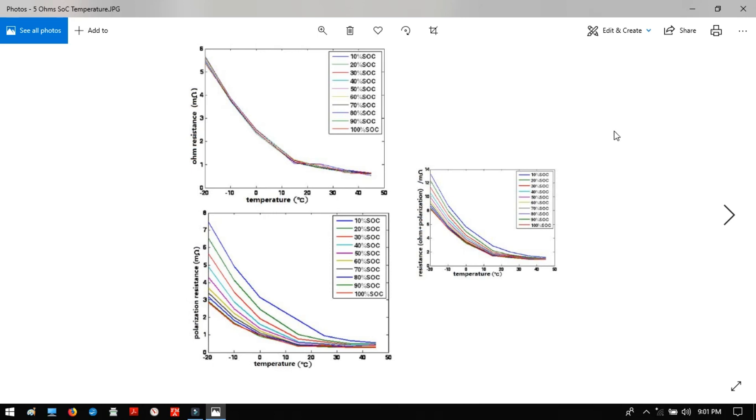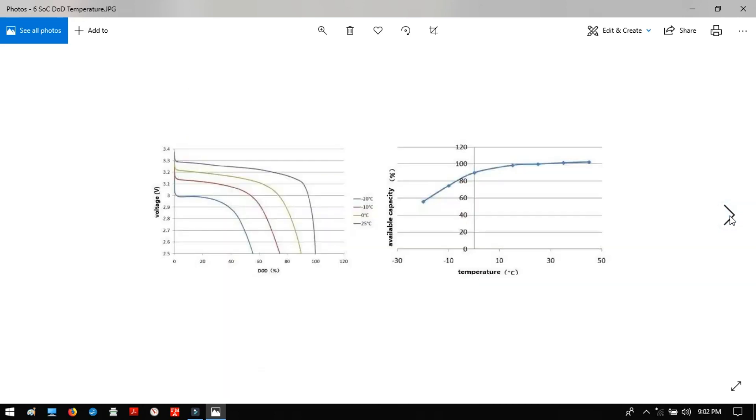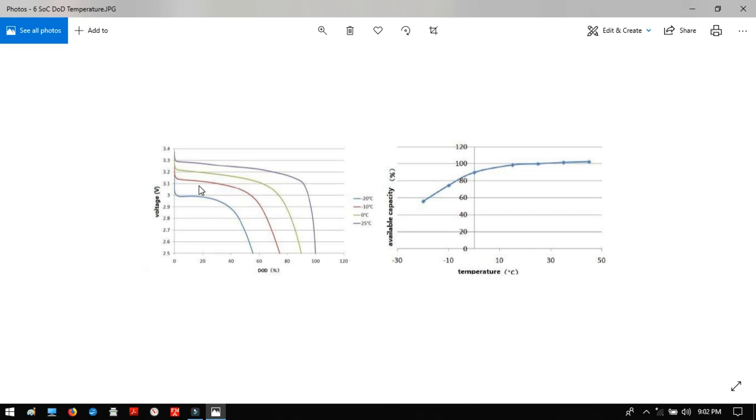Now, that happens for a couple of reasons. One is that we get this increase in ohms. Now, that can be like conventional DC ohms or polarization resistance, also measured in ohms. But the two effects combine into this chart over here. And we see that as the temperature goes down, your ohms go up from both sources there. And as your state of charge changes, it also changes. So in this case, it's actually inverse. So the lower the state of charge, the higher the ohms, which will mean that you will have a greater voltage change under load, voltage drop.